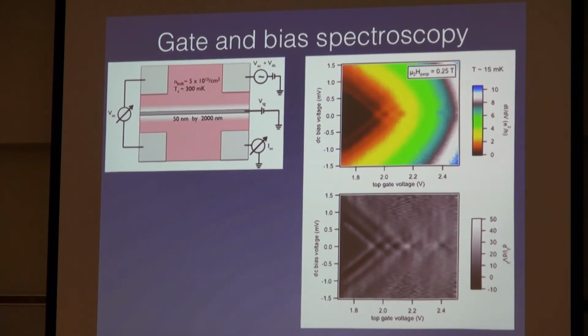So we put the ions in place. We have to do this at room temperature because at low temperatures, the ions are frozen out. So what you do is set it at room temperature, you cool the device down. The conduction is set in these pink regions, and then we're going to look at the transport properties over voltage biases and measure the current that flows through this device. We're going to measure the current that we set up in this device as a function of this gate voltage.